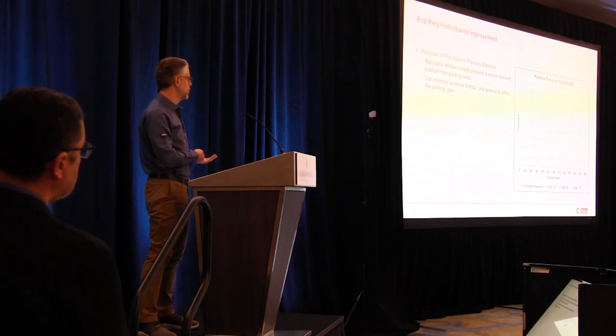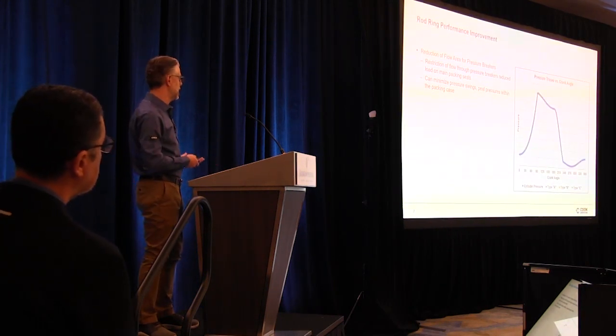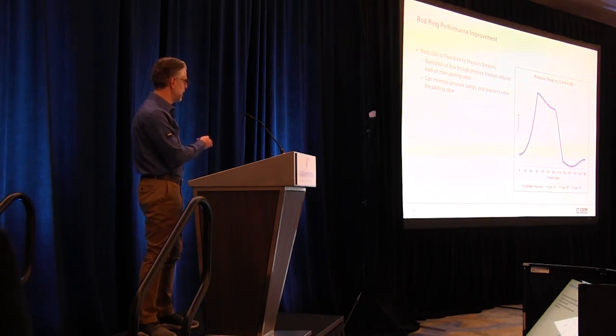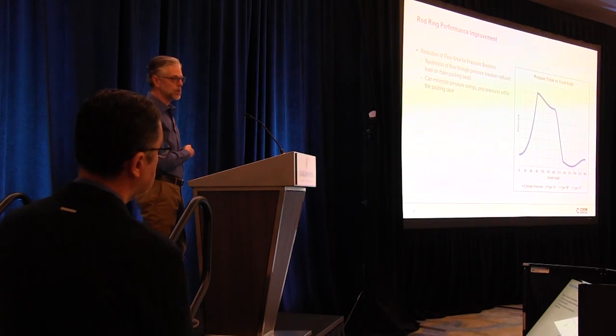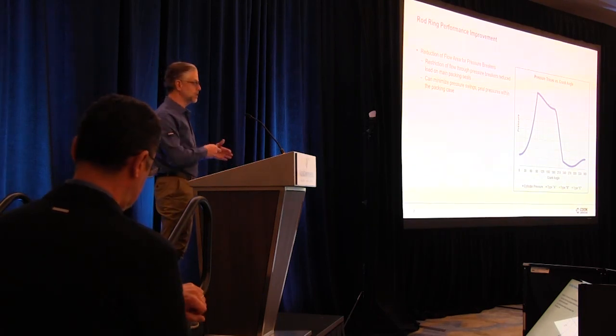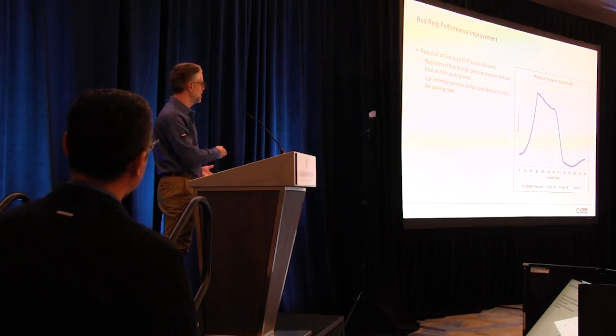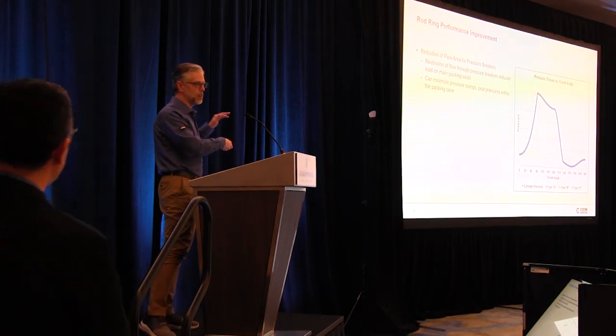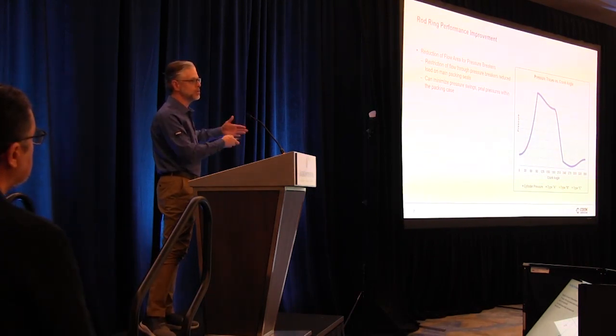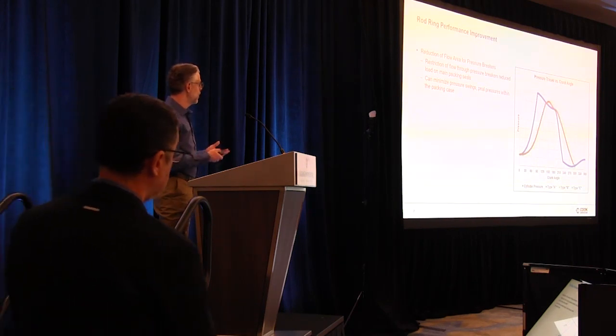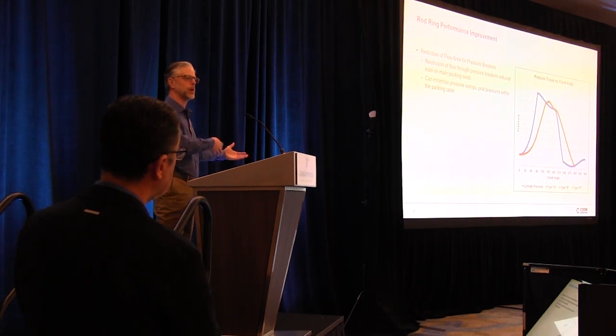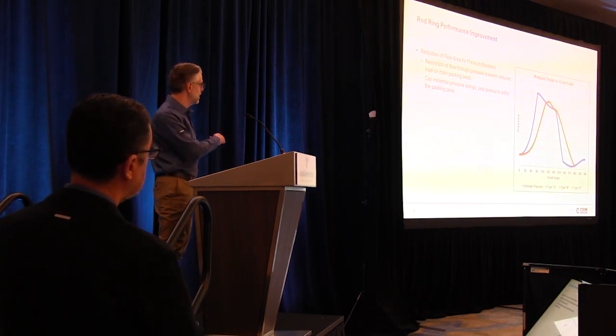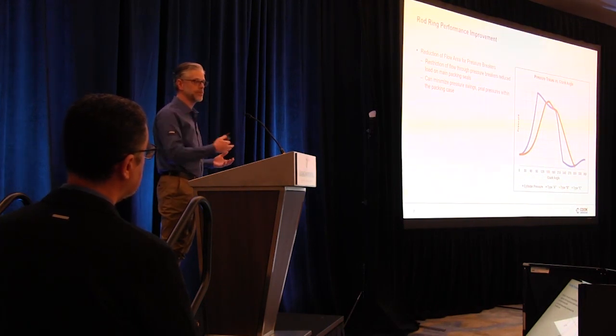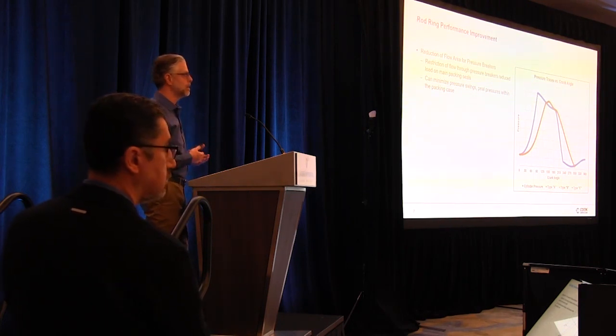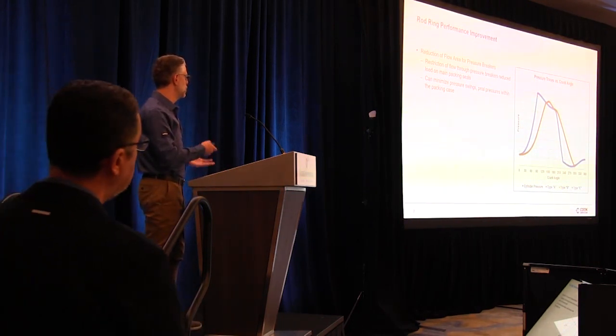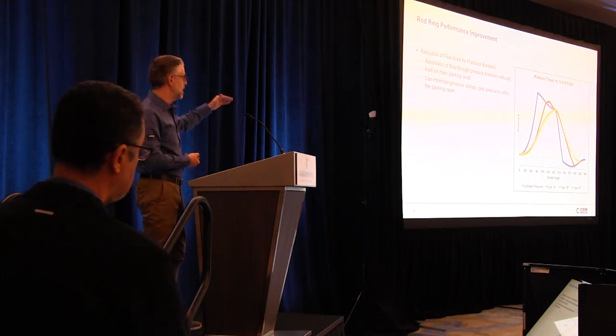And then we have similar tools that we're bringing to look at the packing. So as we look at packing, one of the things we look at is how do we change the PV curve that you see in the cylinder to what you see in the packing, right? So this may be a typical PV curve that you would see in your cylinder. How do you smooth that out with the first couple of packing rings to reduce the stress and the load on your packing rings? So with hydrogen gas, the typical pressure breaker that you might put in that packing case isn't really having much impact here, because the gas is just flowing through that orifice extremely readily and it's just not impacting that. So we're working on new mechanical designs that continue to bring that down and to smooth that